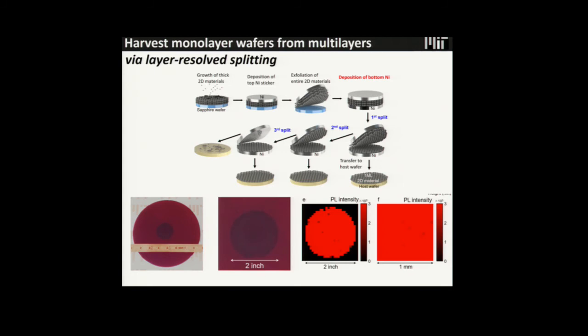Also, why this is so meaningful is that typically, in order to grow monolayer all over the wafer, it takes a really long time to get rid of the nuclei on top of the existing nuclei. So there is a way to grow completely monolayer 2D material on the wafer, but it takes a really long time. So this relieves that kind of stress. Whatever, you just grow really thick, then you just split them out. That's our strategy.